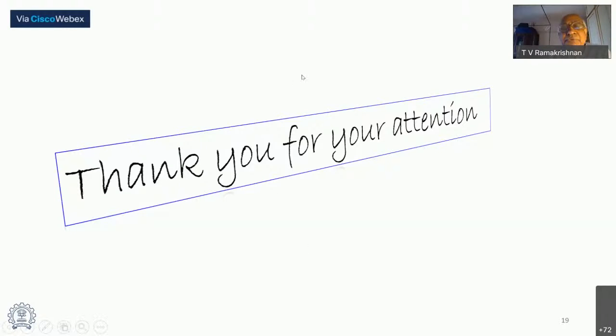Thanks. Is there anyone else who would like to ask? May I just interject, DD? Avinash, with respect to the question that Sampath asked about the ordering, in the Rietveld analysis, the superlattice peak intensity is related to the extent of ordering. So do you get 100% ordering or close to 100%, which would imply then it cannot be described as some parts being disordered, some parts being ordered? Yeah, the intensities actually match in the Rietveld, they match 100%. Which means that it's nearly 100% ordered. So that would answer the question that Sampath was raising. Yeah. However, this is still from a powder sample, so I would not go so far. However, there is no evidence of glassy behavior. That is sure.